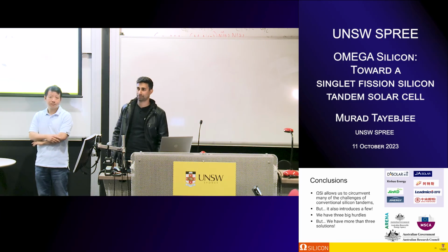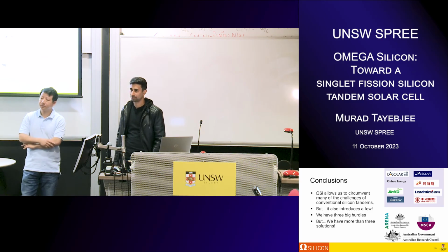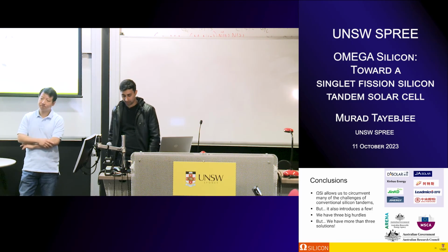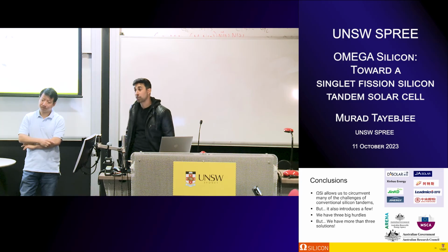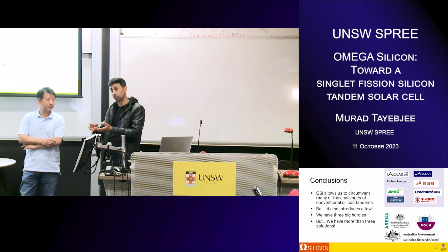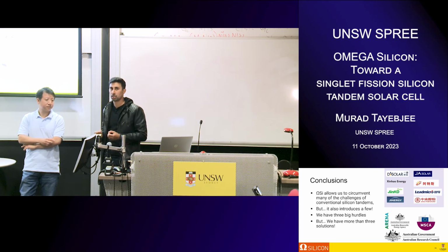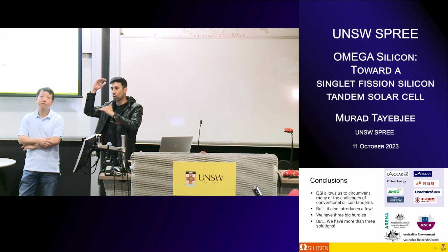Thank you. Hey, thanks for the talk. So do you think there would be an inorganic material with the same properties, or is this something that is exclusive to organic? So multiple exciton generation occurs in inorganic quantum dots for a similar reason, right? Because you start to confine your electronic states, and then you have discrete energy levels, and then you're able to undergo multiple exciton generation. In most of those systems, they have heavy atoms, which means that spin is not a good quantum number. So there's nothing to stop that first.